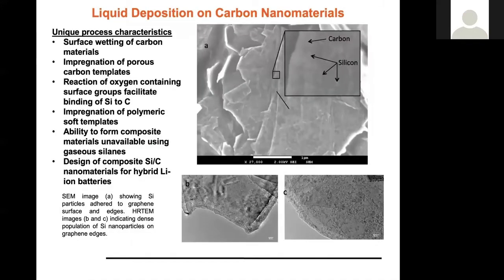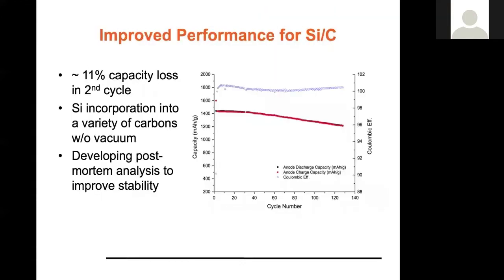In addition to making silicon nanowires, we can use the fact that CHS is a liquid to our advantage by directly wetting a wide variety of carbon nanomaterials to make silicon carbon composites. We can use this liquid deposition to wet the carbon nanomaterials, do the deposition, and create carbon silicon composites easily. And so we see much better capacity retention over 120 cycles now. Earlier we saw a large capacity fade, and here we have very good cycling, even up to and past 60 cycles.